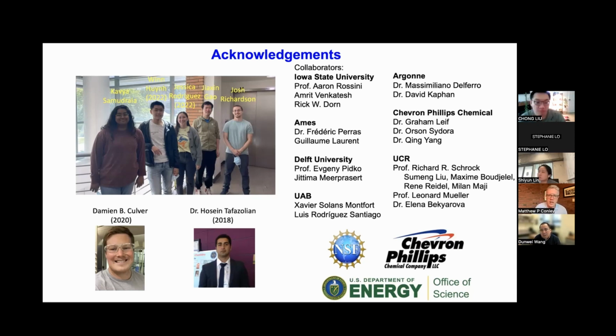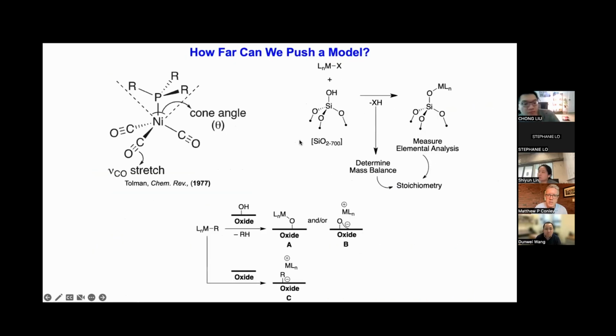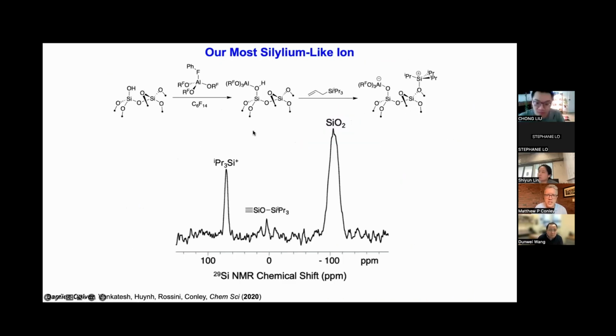So I showed, let me see if I can get back to it. I showed an example. So this Bronsted acid site has a characteristic OH stretch. It has a characteristic proton NMR chemical shift, a characteristic aluminum NMR set of properties. And we developed a small cluster that's just based off a polysilsesquioxane model, where we basically put on this Lewis acid, and then all of those parameters fit very well to what we were seeing experimentally.